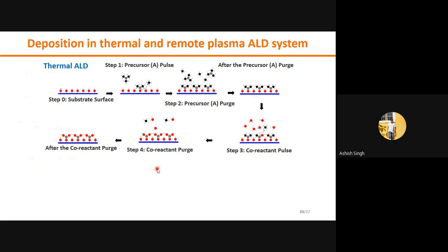Our ALD system is plasma as well as thermal ALD. We are using a hybrid ALD system, in which we can use thermal as well as plasma ALD. First we are going to see thermal ALD. This is our substrate with unsaturated bonds, which can be called dangling bonds. We first put in the precursor. The precursor will go and sit on the dangling bonds and make bonds with them, and then some unreacted precursor will also be there in the chamber that we need to remove.